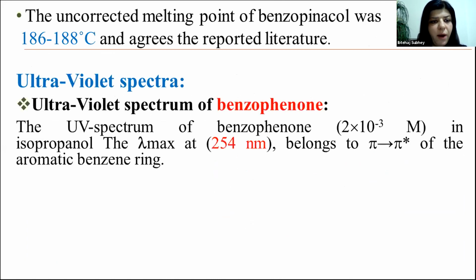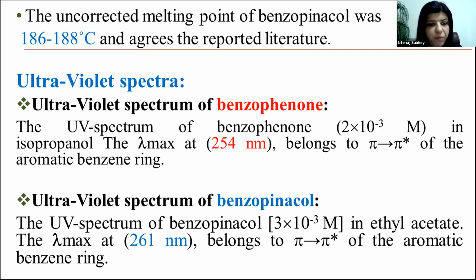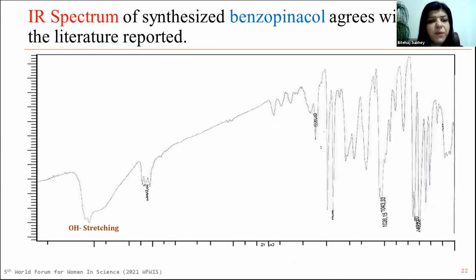UV visible spectrum. The UV spectrum of benzophenone, measured in isopropanol as the solvent, has its lambda max at 254 nanometers, which belongs to pi star of the aromatic benzene ring, and the UV spectrum of benzopinacol in ethyl acetate has its lambda max at 261 nanometers, which belongs to pi star of the aromatic benzene ring. This figure shows the IR spectrum of benzopinacol that's synthesized. This band refers to the OH stretching found in the structure of benzopinacol.